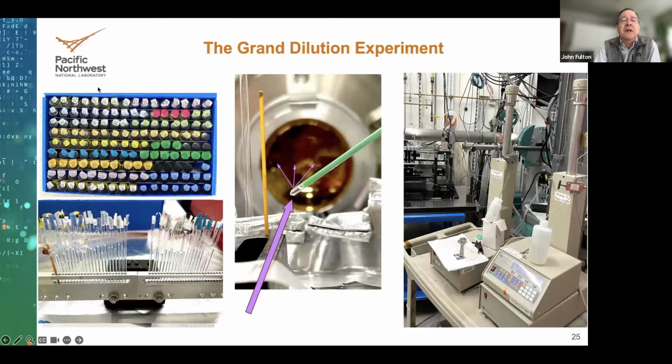We've made lots of measurements. The conventional technique is to prepare hundreds of solutions of different electrolytes at different concentrations, load them into capillaries, and run multiple series overnight or during the day. Another method that we've used to some advantage is to prepare two stepper-motor-driven syringe pumps. We have electrolyte in one, water in the other. We can set up a continuous ramp, and then we can continuously measure the scattering from these solutions.